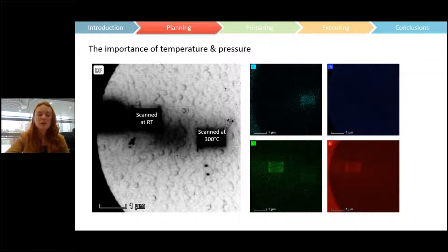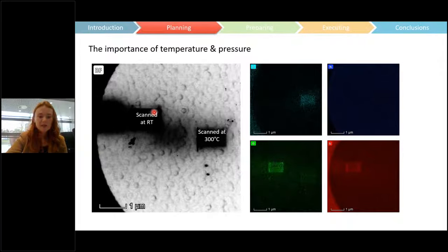You can see this on the image on the left, you can see the circle, which is the window of our chip. And you can see two areas. One has been scanned at room temperature, and one has been scanned at 300 degrees. I'm just going to put the pointer on, actually, and that'll make it easier. One has been scanned at room temperature, and one has been scanned at 300 degrees. And you can see contamination in both locations. And it ruined our experiment, which, okay, fine, it was a Friday afternoon experiment. We weren't expecting much from it.